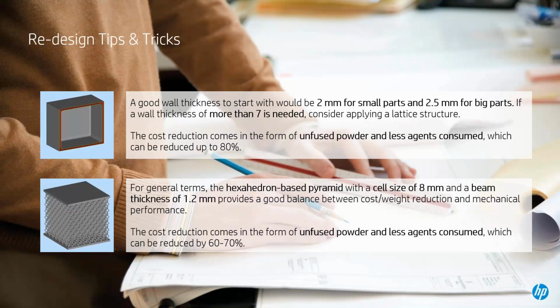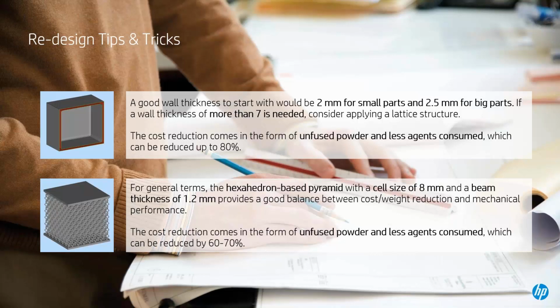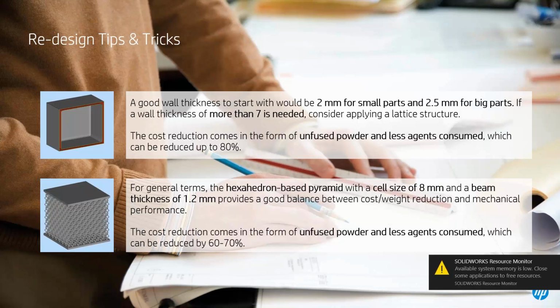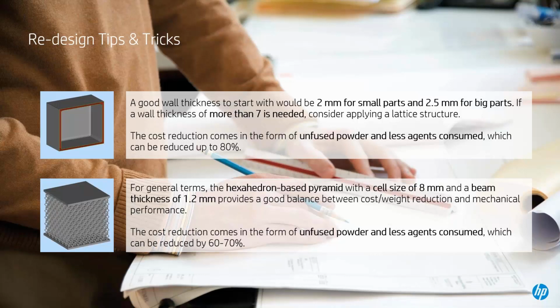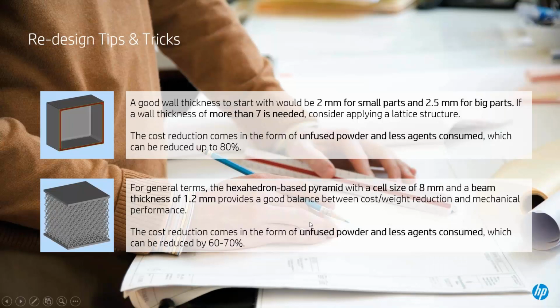When we look at hollowing of parts, typically we say you should start to look at hollowing a part when it comes up to about 7 millimeters thick, right? As we start to go thicker, we'll definitely need to hollow the part out. But a good wall thickness for hollowing is about 2 millimeters. So anywhere between 2 and 3 millimeters is a good wall thickness for hollowing out parts.